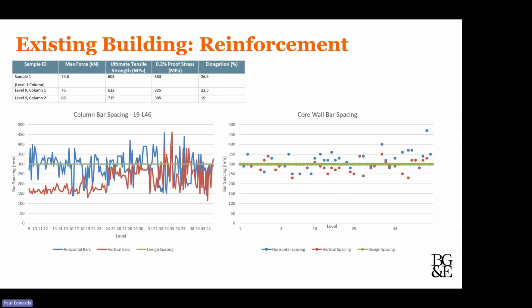And so the team undertook assessments of the existing reinforcement, both to understand grade, but also to understand spacing and lap distances. And this was done using calibrated cover meters for columns and cores, and generally one or two areas, but generally everything was found to be acceptable and in accordance with design standards as far as that was concerned.